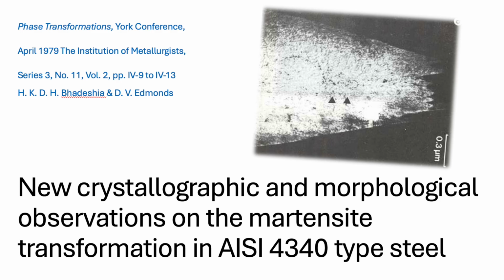Why is that limited nature important? What does it tell us? It suggests the principle of least effort. Again, twinning was most common when adjacent martensite units were already in a twin relationship. Ah, so if the neighbors were already aligned in a way that helped manage the strain mismatch. Correct. If the local environment already provided some strain accommodation through that existing twin relationship, the growing plate didn't need to go to the energetic trouble of creating lots of new, complex internal twins. Especially since these plates form at higher temperatures, where the driving force for transformation is a bit lower anyway. Precisely. It all fits together.